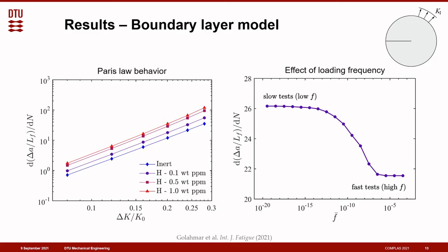In addition, as you can see in the left figure, the model is capable of naturally providing as an output the Paris law behavior and the role of hydrogen on it. So what we have here is the fatigue crack growth rates, or basically the speed of the fatigue crack growth, as a function of the normalized stress intensity factor. So for a given stress intensity factor, faster fatigue crack growth is observed as the hydrogen content is increased.